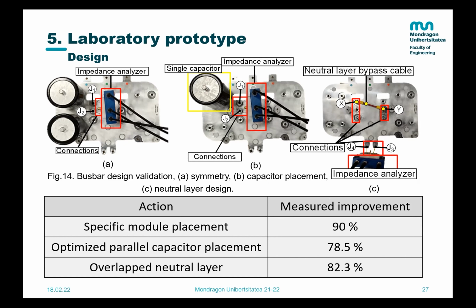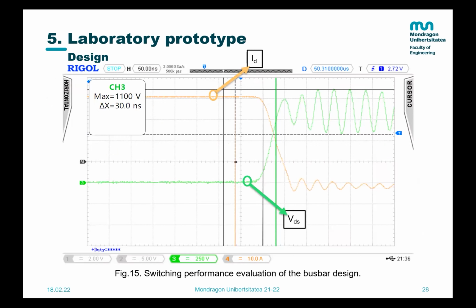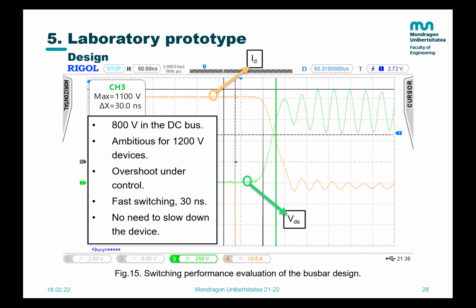The last step was to test this design and actually switch the bus bar. This is the waveform we obtained from the double pulse testing. We were able to switch up to 800 volts, which is a very ambitious voltage for 1200 volt devices, but we could do this because the overvoltage was under control. And we saw that we were still switching very fast, in around 30 nanoseconds, which is a very high switching speed for high power modules.